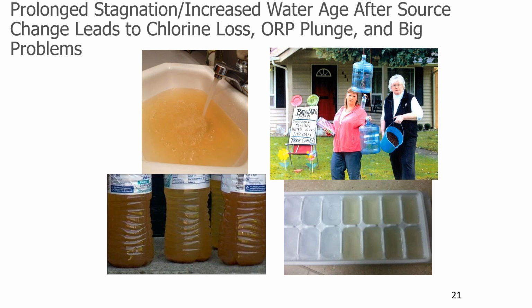These are community activists that would go around following the flushing crews and scoop up all the material that was flushed out of the pipes and accumulated on the streets and bring bucket loads of this material to the city council meetings. It was very contentious and difficult, and it was determined that this was all due to hydraulic mounding and complete loss of residual chlorine and a negative oxidation reduction potential, and this was reversible once it got auto flushers, kept the water moving, gently flushed the pipes, not breaking up the tubercles even more, and eventually they did have to do some main replacement. These were old, corroded mains and needed some service.